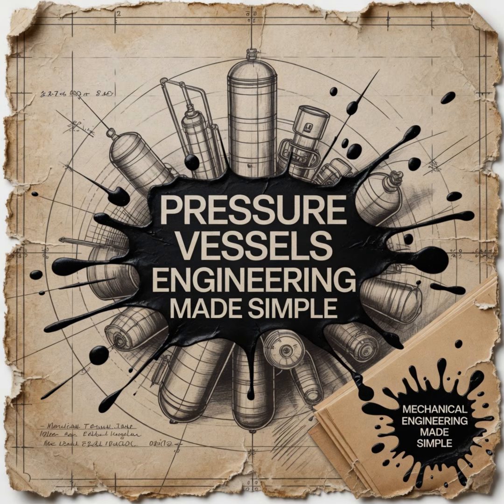Oh, I see. Yeah, if that tight crack is oriented perpendicular to the incoming radiation beam, the radiation just passes through the full thickness of the steel as if the crack wasn't there. There is no missing density, so the crack does not show up on the film at all. You could have a lethal crack running the length of the weld, and the X-ray would show a perfect, clear picture. That's genuinely terrifying. Which is exactly why UT is so critical.